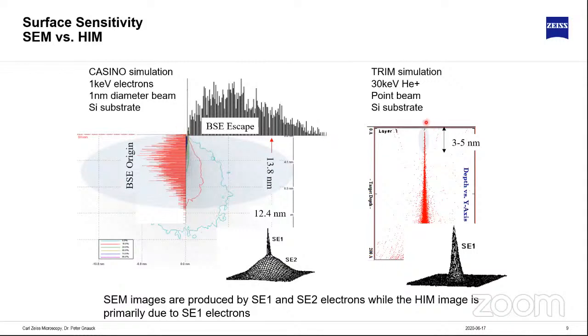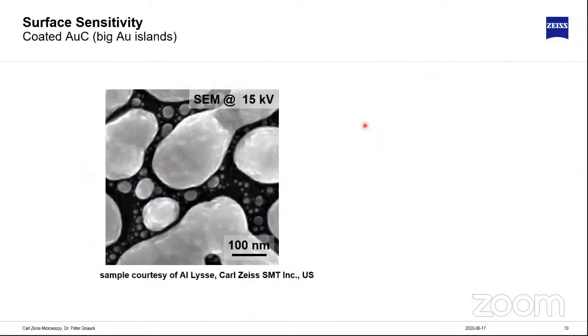If we look at helium ions that are hitting a sample, what happens is on impact, again, they will generate a secondary electron, the SE1 electron. But what then happens is the following: the ions are much slower, even at 30 keV compared to an electron beam, because they're much heavier. So they cannot transfer their energy to other electrons inside the sample, and they cannot really generate backscattered electrons. That means the only signal that we get is the signal from the impact, and that means we only get an SE1 information, no matter what the beam energy is. We're always extremely surface sensitive. And I'd like to show you a comparison between electron beam imaging and ion beam imaging.